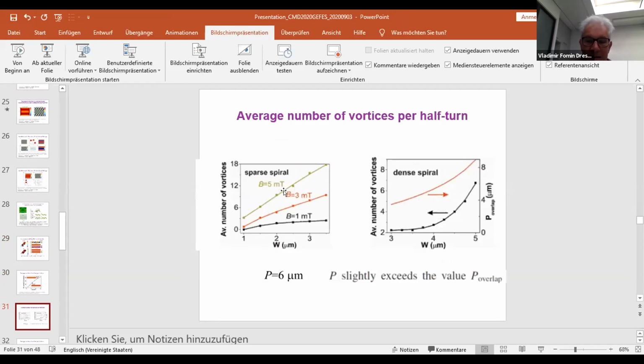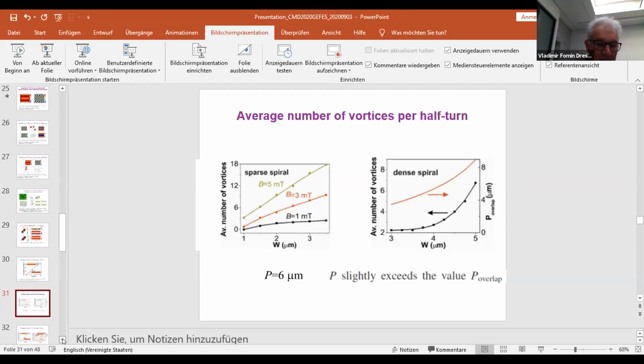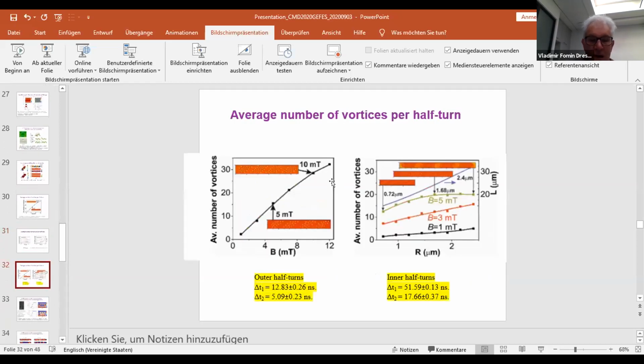Depending on the geometry of a spiral, we can have different dependence of the average number of vortices on the widths. For a sparse spiral, it is sublinear. For a dense spiral, it's superlinear. But what is interesting here for the future, if we calculate the dynamics of these vortices, then these characteristic times, time of flight and time of nucleation, are different in outer half turns and in inner half turns. So the nanospiral behaves differently in different places as concerns the dynamics of vortices.